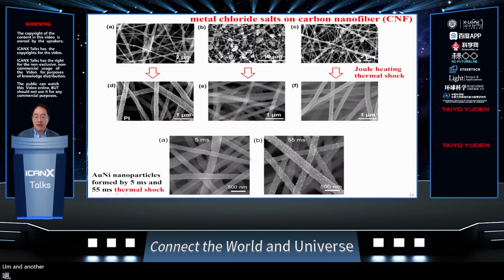And another thing that we noted was that the faster the carbothermal shock, the more uniform and smaller the nanoparticle size is. And that was quite surprising. For one, the temperature we're talking about is extremely high. At that temperature, these metal particles should be molten. But according to Ostwald ripening theory, these particles should actually grow at this high temperature to minimize the surface energy. So we don't understand why they are such fine nanoparticles.